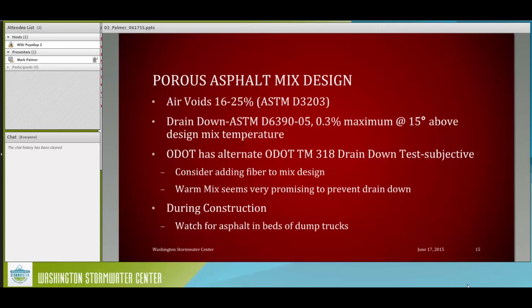As a field check for that, you'll want to watch for asphalt in the beds of dump trucks to see if you're getting a lot of asphalt liquid in the bottom of your trucks. If you are, then you need to stop, readjust your mix, and try to start again.